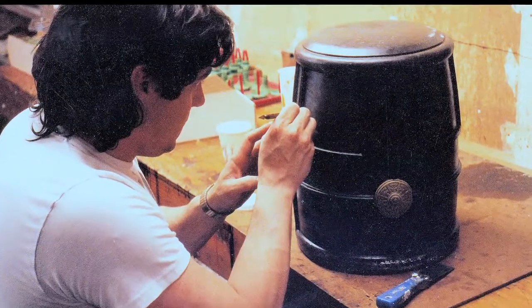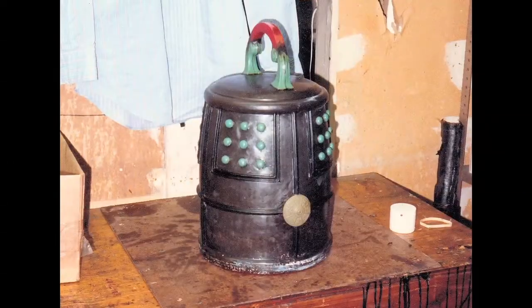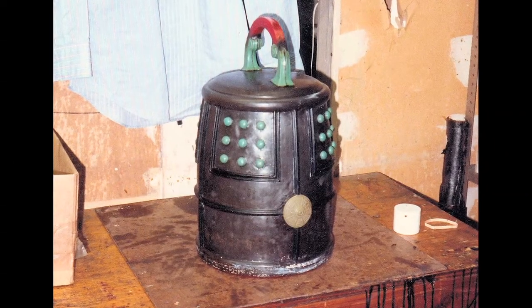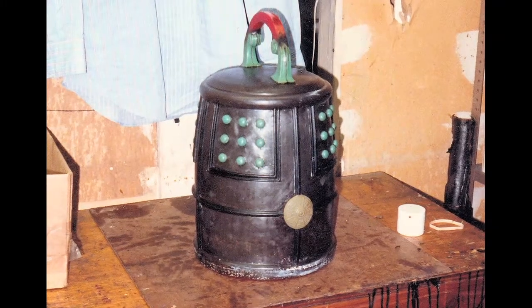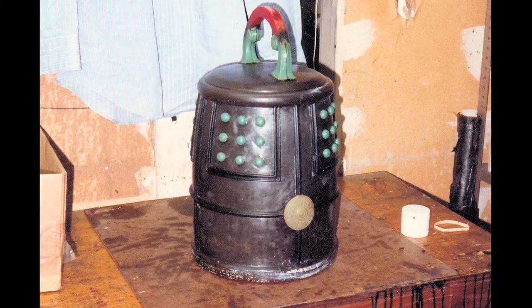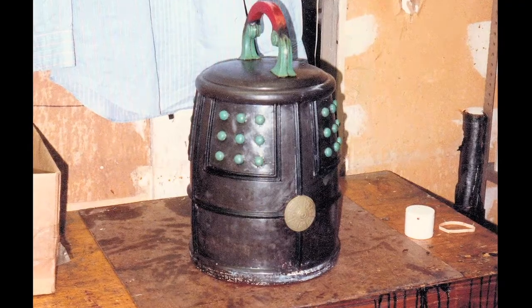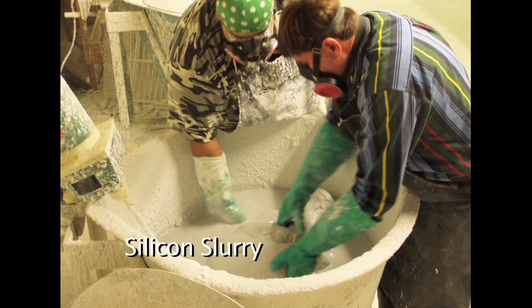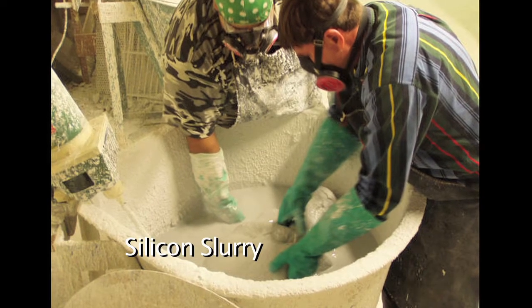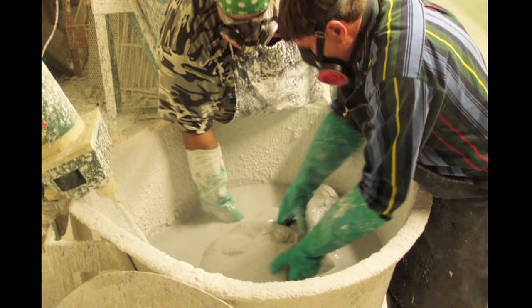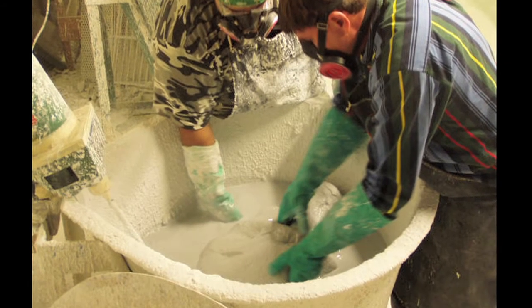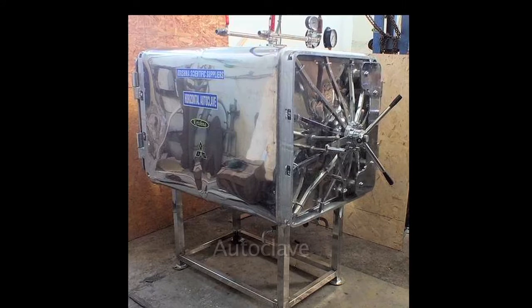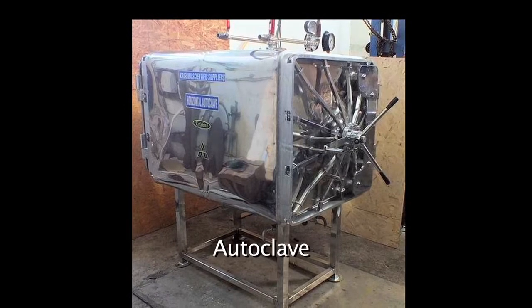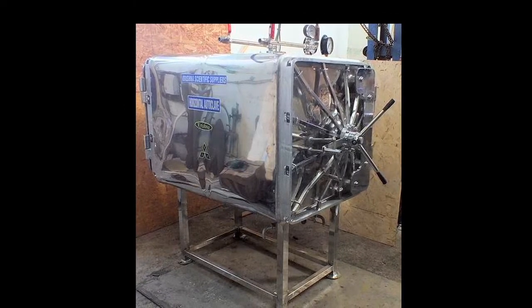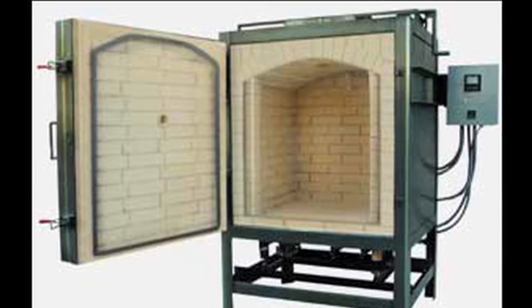Now that the wax positive was complete, I made a ceramic shell negative by dipping the wax pattern into a silica slurry, then applying sand to it to gradually build up the shell. I repeated this process daily for 12 coats, adding a stainless steel wire mesh at the 8th coat for structural stability. Once the shell was complete, we placed it in an autoclave to melt out the wax, hence the lost wax method, then fired it in a kiln.